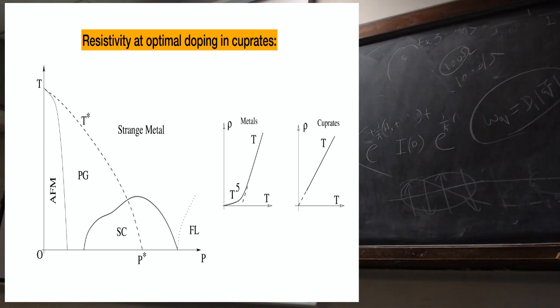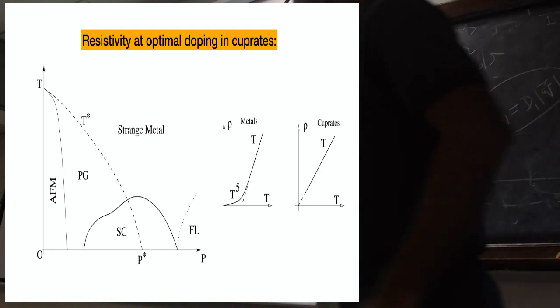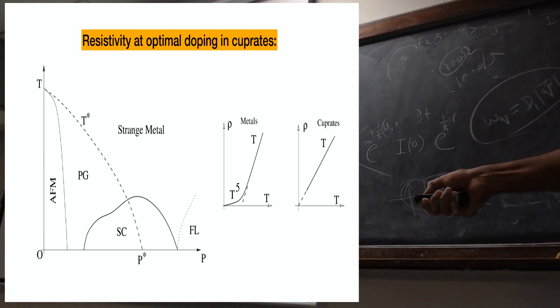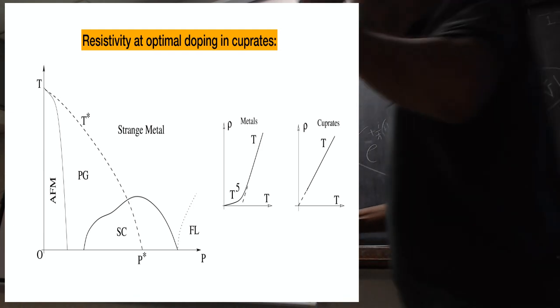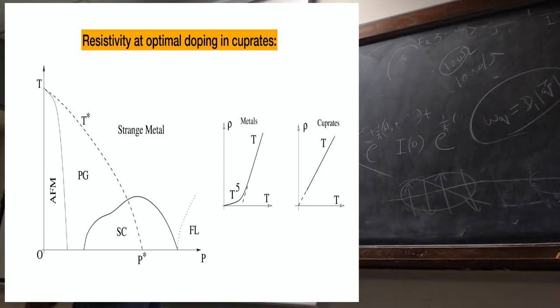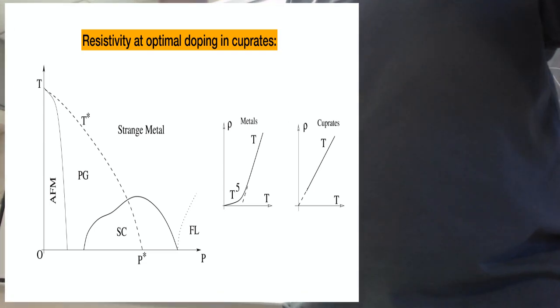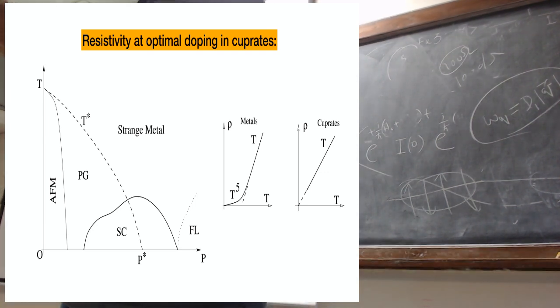Paramagnons are like on top of the main paramagnons. Close to P star, you have already lost the Fermi surface. That's the whole problem. The point is that nobody understood what the pseudogap is. What they do know is that in this region, up at room temperature, up to 5 lattice sites, where one lattice site is 4 angstrom, up to 20 angstrom, that length scale, the spins are correlated. Then they become uncorrelated. Then another patch.